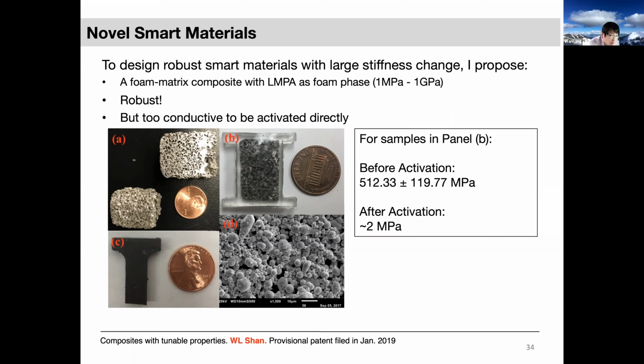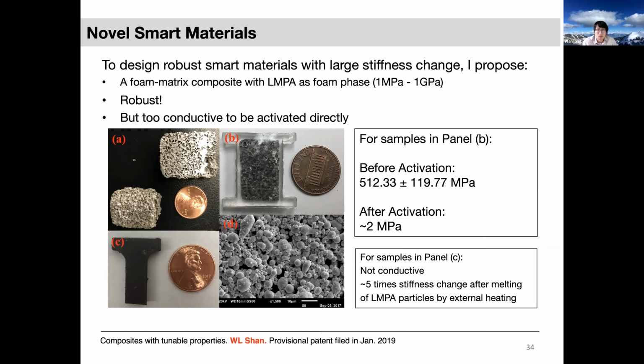But the problem is that this is too conductive to be activated directly. The electrical resistance is literally 0. You cannot activate this by joule heating through the composite itself. You have to do external heating, which means you can wrap around a heater to do activation. So I'm gonna talk about one application based on this material when we get there, roughly in 10 slides.